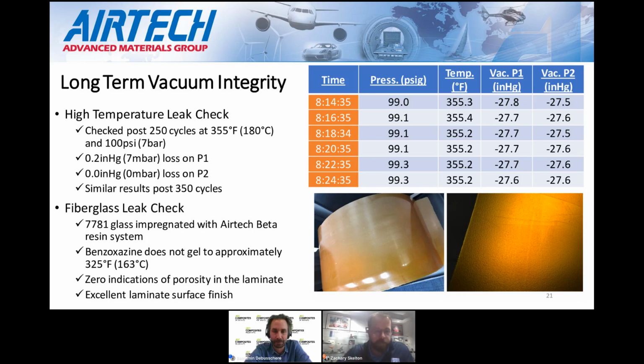Again, sorry, this is not in metric units, but vacuum probe 1 dropped about 0.2 inches of mercury, or about 7 millibar. Vacuum probe 2 dropped to, it kind of fluctuated, we'll call it 0. But again, vacuum is shut off at temperature and pressure. So very well within any specs for vacuum integrity.